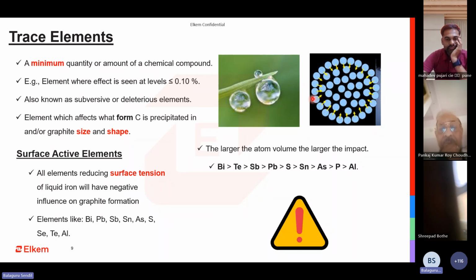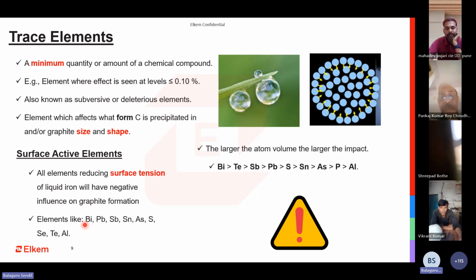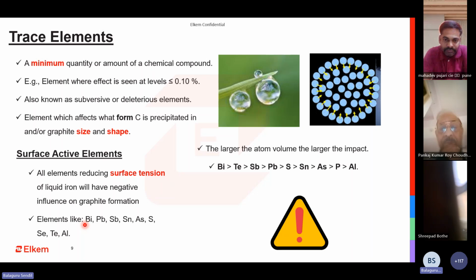One thing is that this is the hierarchy in which it does. So all these elements will not have the same impact. When we discussed pearlite promoting elements, we know for a fact copper is much stronger in promoting pearlite than manganese. And then we have antimony and arsenic, which are much stronger than even copper. So this is the way in which it is promoting. Similarly, there is a way in which these elements can damage the surface tension. Bismuth is more damaging to the surface tension. This is not always a bad thing. This is also a good thing.